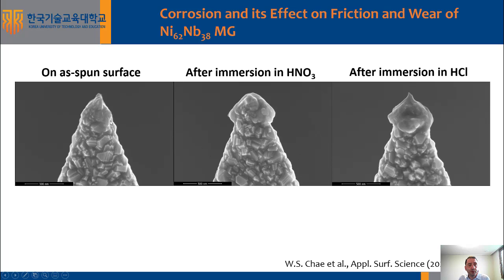After these measurements, we then imaged the used tips on the different surfaces by scanning electron microscopy, and we indeed find that the amount of transferred material at the end of the tip increases after immersion into acid, and that the amount of transferred material is the largest after immersion in hydrochloric acid.